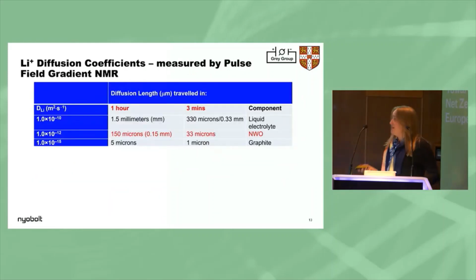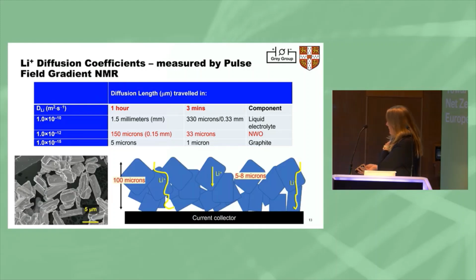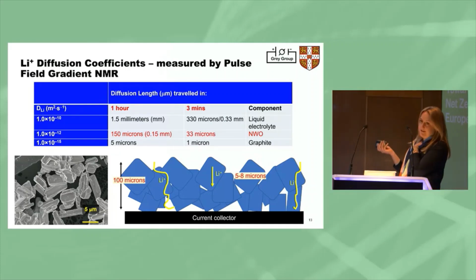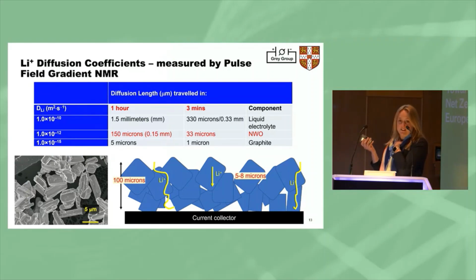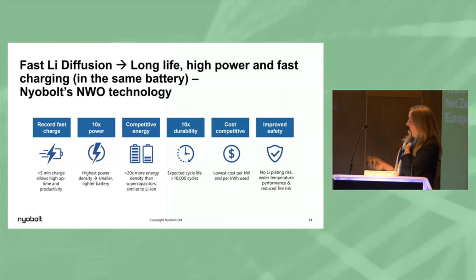So obviously we know Claire and her group do a lot of NMR, so they employed this technique to understand exactly what's happening with that lithium ion diffusion. And really what was seen was that in 3 minutes a lithium ion can travel 33 microns through an NWO particle. So that's pretty impressive. And it means that you don't necessarily need to worry about having a small particle while maintaining a fast charge. So that fast diffusion through the particle really does enable you to have that fast charge without losing the cycle life. So fast lithium ion diffusion, long life, high power, and fast charging in the same battery.